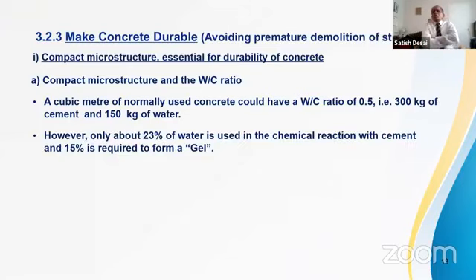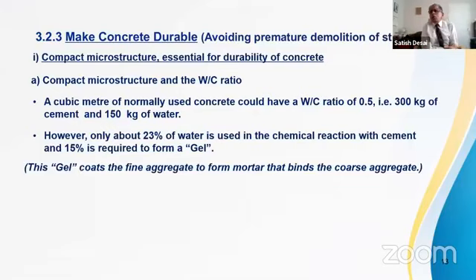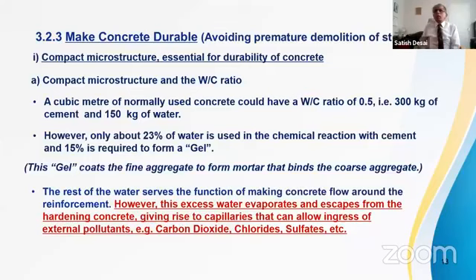But only 23% of the water is used in chemical reaction with cement, and 15% is required to form a gel. This gel coats fine aggregate to form mortar that binds the coarse aggregate, and you get the hardened mass we call concrete. But the rest of the water serves only the function of making concrete flow around the reinforcement. That is, making concrete workable. But this excess water evaporates and escapes from the hardening concrete, and what you get is capillaries which allow ingress of external pollutants, carbon dioxide, chloride, sulfates, etc.